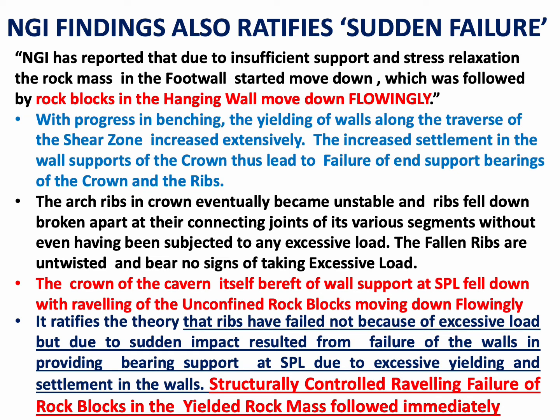It ratifies the theory that the ribs have fallen not because of the excessive load, but due to sudden impact resulting from failure of the walls in providing any bearing support at the SPL due to the excessive yielding and settlement in the walls. Structurally controlled raveling failure of the rock blocks in the yielded rock mass followed immediately. Once the wall failed providing bearing to the crown, the structurally controlled raveling failure of the rock blocks in the crown in the yielded rock mass followed immediately.